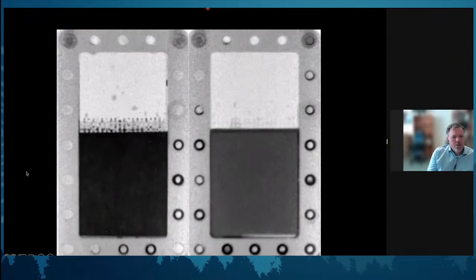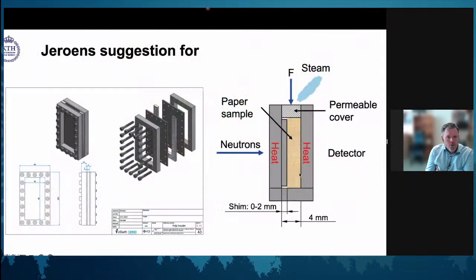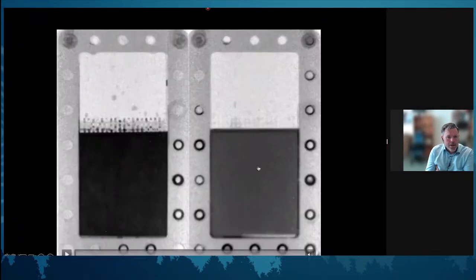So now we're seeing neutrons that have passed through our paper sample. We are looking from one side, the neutrons come from the other. We have two cases here. The left one is a 2 millimeter wide slit. So it's 4 millimeter thickness, and we have a shim that is 2. So that's half of this void is now filled with aluminum shim. And the right one is without aluminum shim.